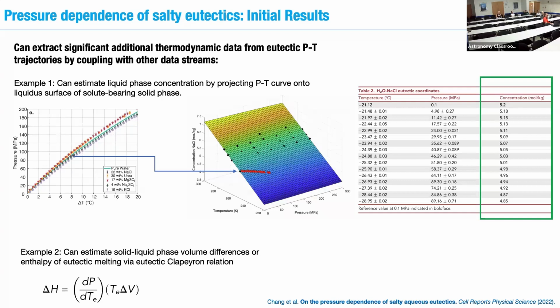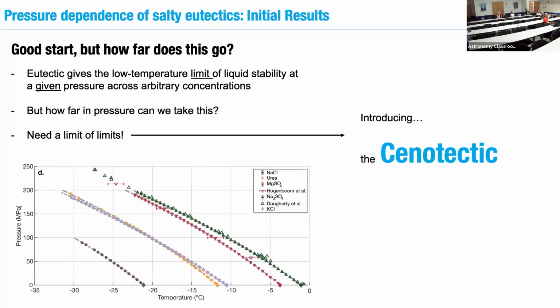And then we could also play thermodynamic tricks applicable to any kind of univariant, first order phase transition. We can play these thermodynamic tricks on the eutectic, so we can apply a Clapeyron relation to this eutectic curve instead of a pure material curve, and back things out like the enthalpy of fusion of the eutectic reaction, or if you have the enthalpy of fusion of the eutectic reaction, you can back out the phase volume difference. So not important, but I'll note that we've barely scratched the surface of how we can just through classical thermodynamic analysis extract more data from these PT eutectic data sets. Something to think about if there's anyone in the audience with a really strong classical thermo background.